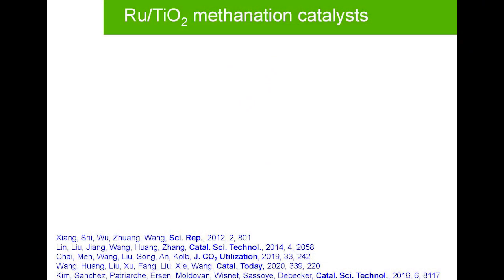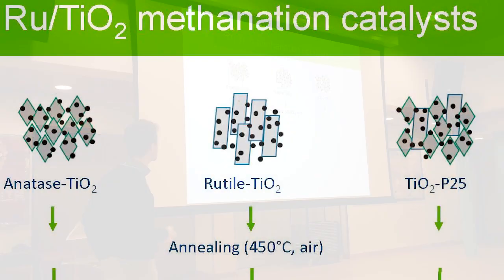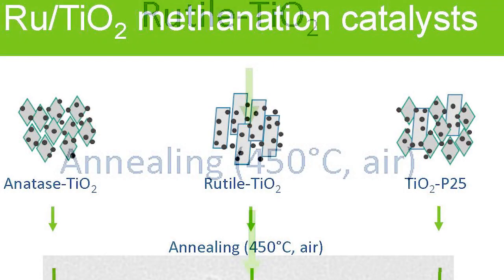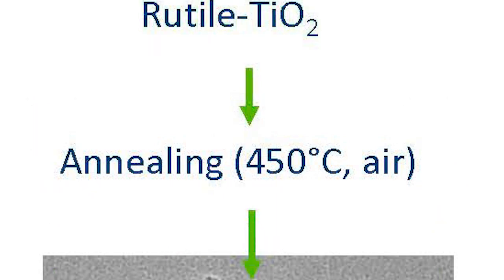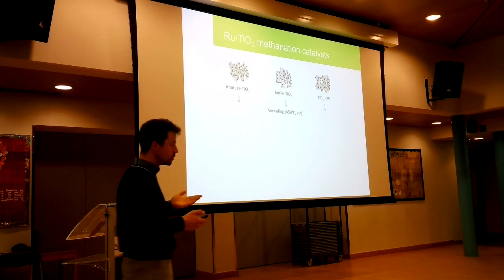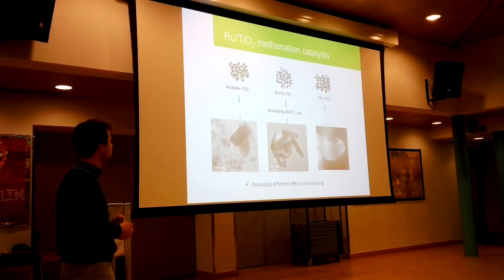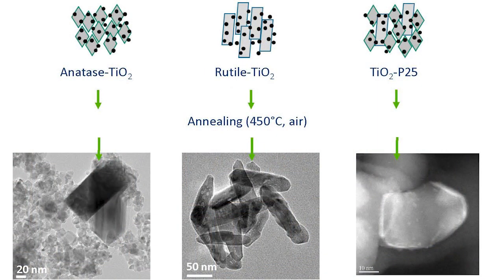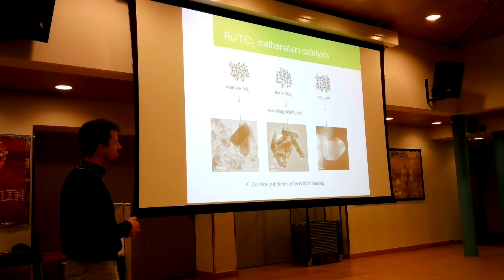We were not the only ones to observe this kind of strange behavior depending on the titania support, so just to mention some references. And we realized that actually it was this step that was responsible for those big differences. If you look at the catalyst after what we call the annealing, so the calcination if you want, you see that those catalysts do not look alike, right?